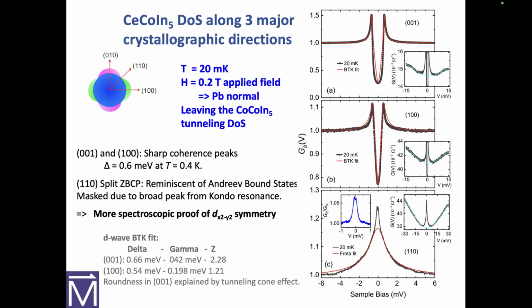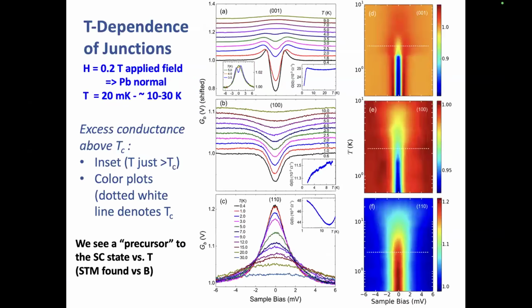When we first started seeing these data, we originally assumed that this peak here was the famed zero bias conductance peak due to the order parameter sign change. We are having trouble fitting that because it's just too broad. So there's something more going on here in this nodal direction than just an Andreev bound state. Here's the detail of the Blonder-Tinkham-Klapwijk fit, and we have good tunnel junctions.